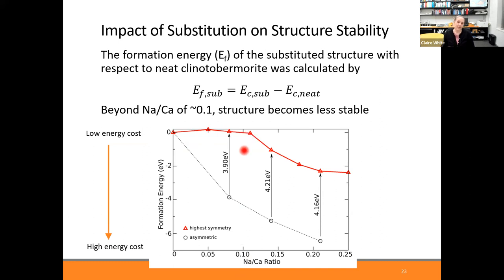And this is interesting. This is giving an indication that you can have some sodium present, but there's a point where you get too much sodium. And so this is likely going to be important from an experimental viewpoint, if you make these concretes, you don't want to dose the system with too much sodium, because it could be causing the gel to be less stable, which could make it more prone to change over time.